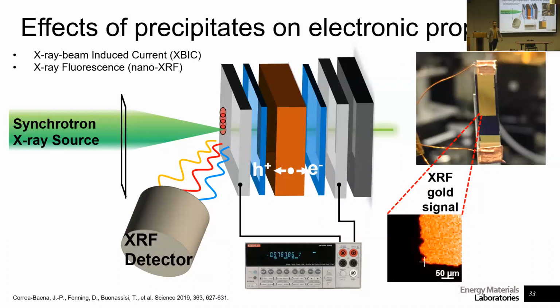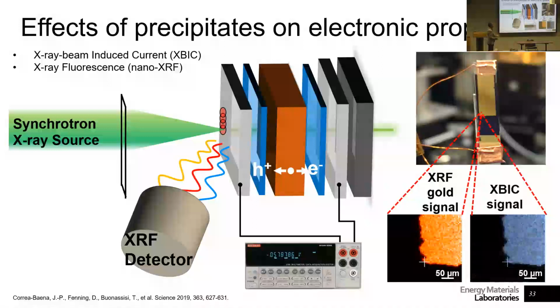In principle, if we're applying a voltage, we should extract a current. And if we're extracting a current, we should be able to see it from X-rays that are being shined. So basically the X-ray, very high energy, comes in and excites an electron, kind of similar to what I showed before. That electron is blasted almost out of the material, but it's not. Then it thermalizes until it gets to the conduction band and gets collected. So what we are seeing here is basically X-rays being transformed into current, which then gives a map that looks like this. That's the XBIC signal, which tells us wherever there's a gold pattern, wherever there's current being passed, we can detect it on a spot by spot basis.